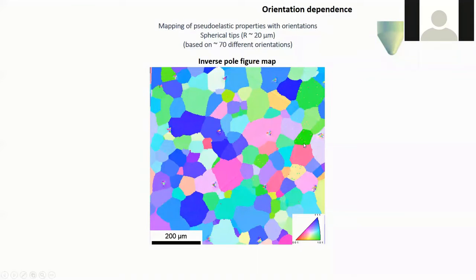So what we did is we smartly used this polycrystalline system, where each of these grains is nothing but a kind of single crystal, and we indented using a spherical indenter with a quite blunt tip. We indented on several of the grains, and these dots here signify some of the representative ones. So this is schematically shown.